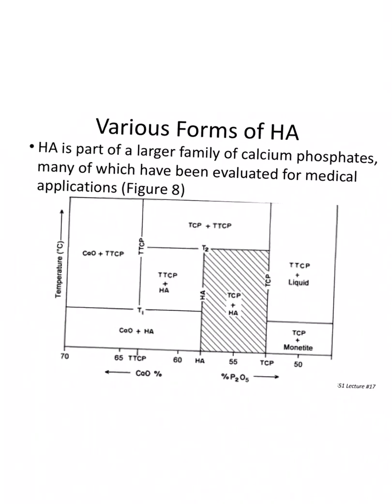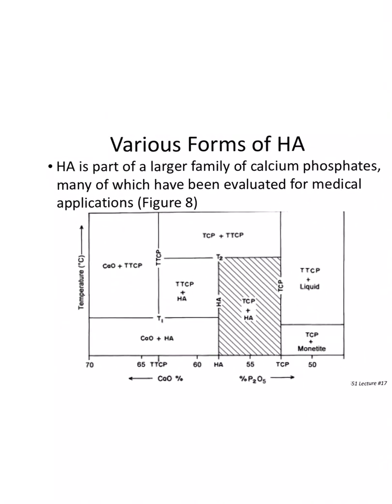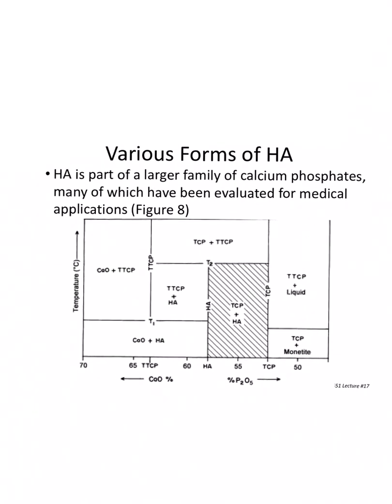And this is all very interesting, but if you dig into this, you'd see that hydroxyapatite is a part of a much larger family of calcium phosphates. And so we'll talk about a lot of these: tetracalcium phosphate, tricalcium phosphate, monetite, which is not very useful. But the thing that we need to note here is that hydroxyapatite is a line compound. Calcium to phosphorus ratio is equal to 1.67.